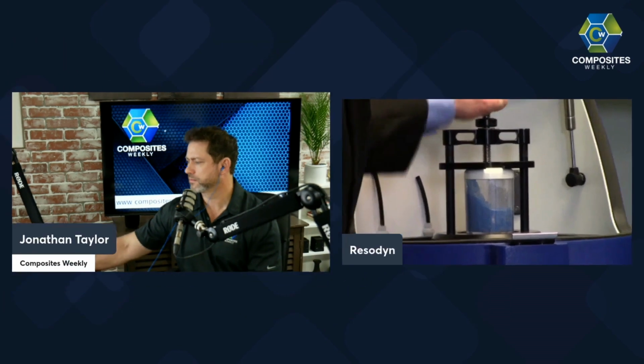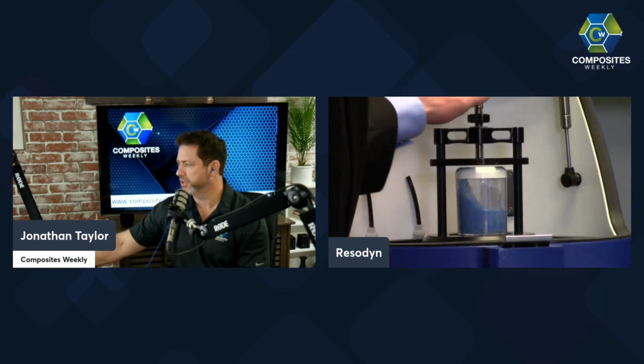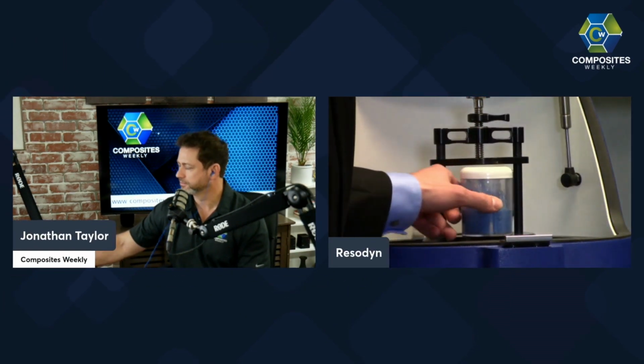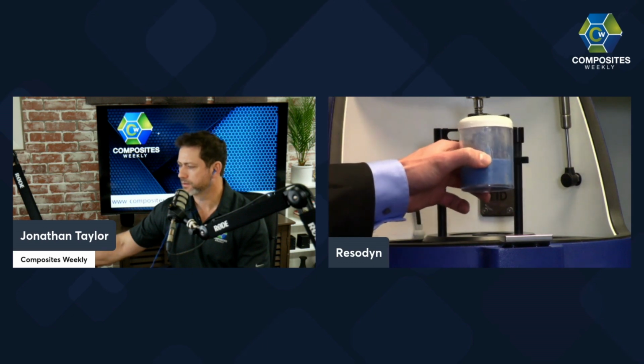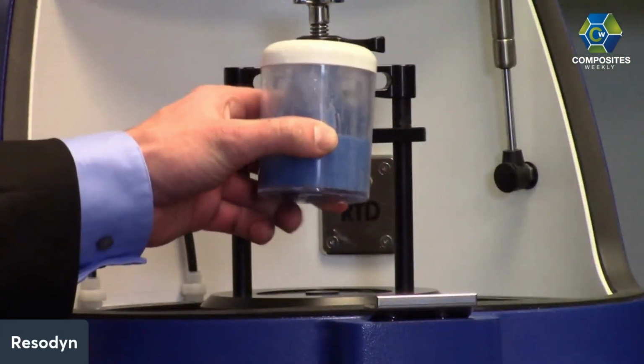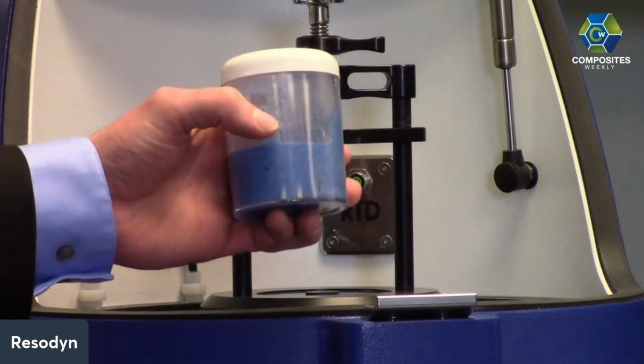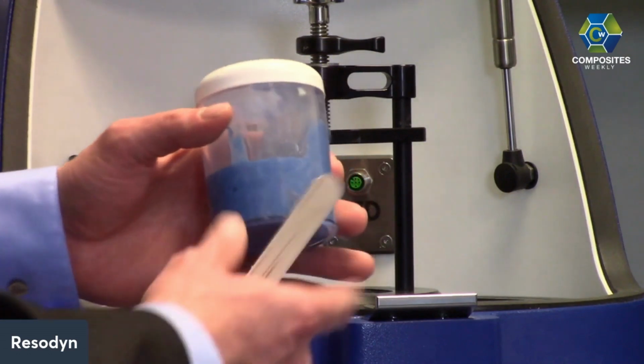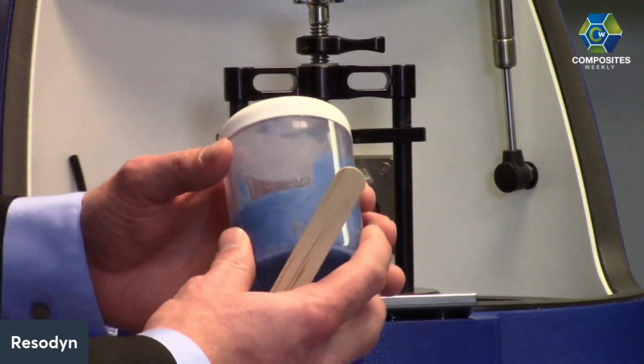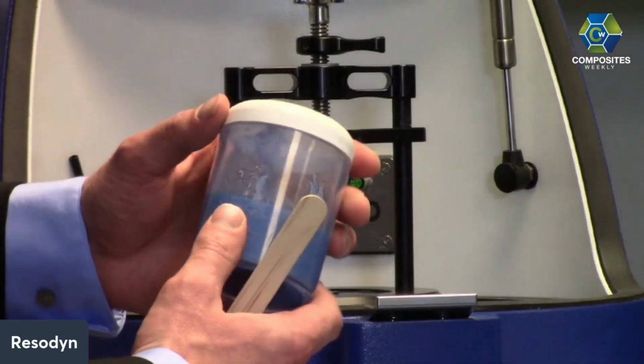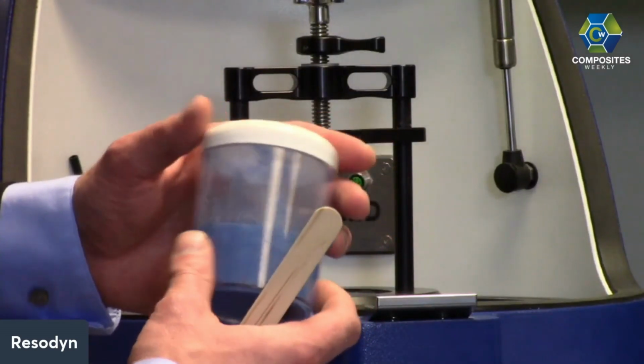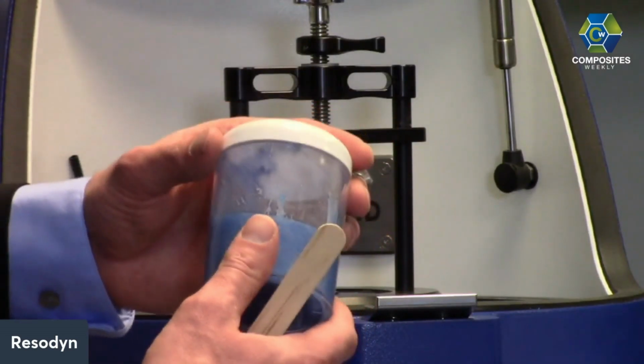So that was 2 minutes of mixing. Yep. And this is about a 350,000 centipoise paste. I think one thing to note that's pretty important is, I'm touching this right now. I've done this mix many times. The temperature rise in this mix after 2 minutes is only around 1 to 2 degrees Celsius.